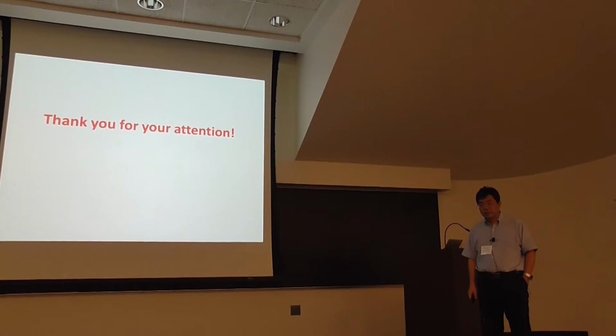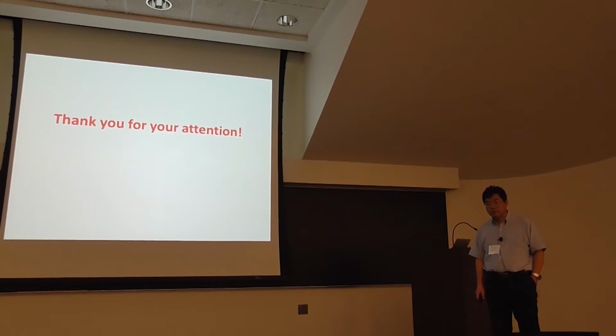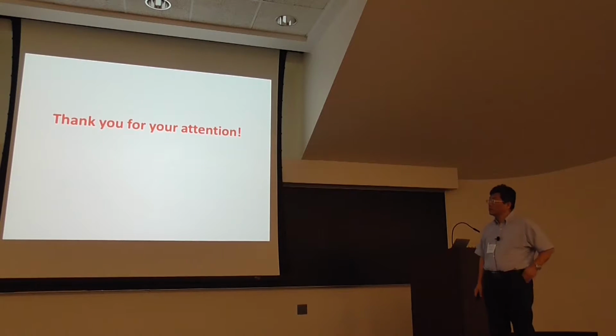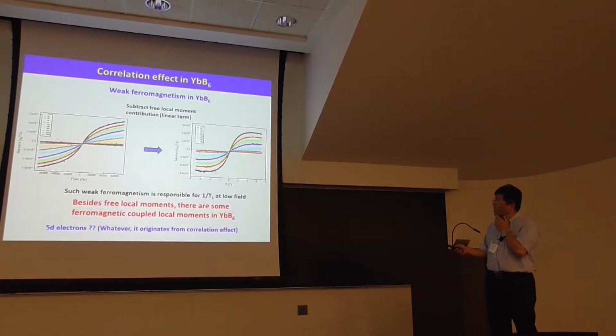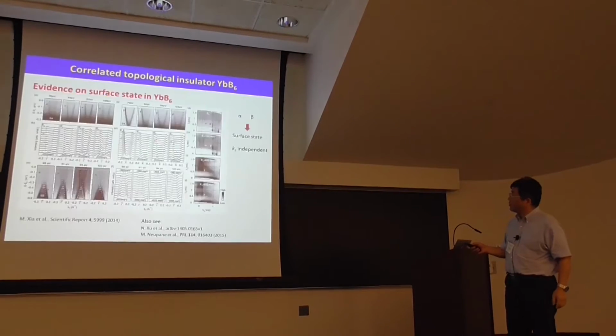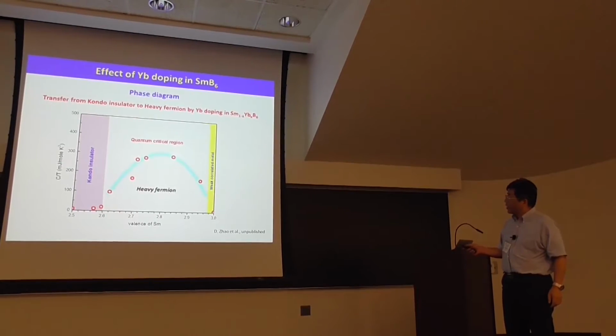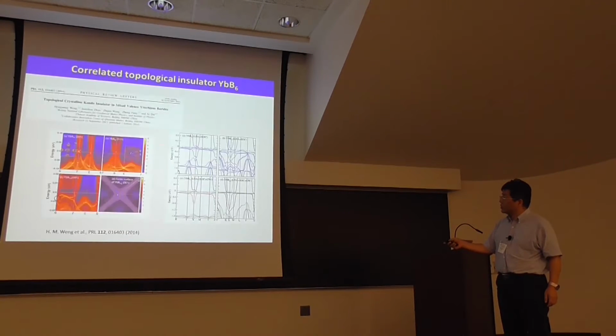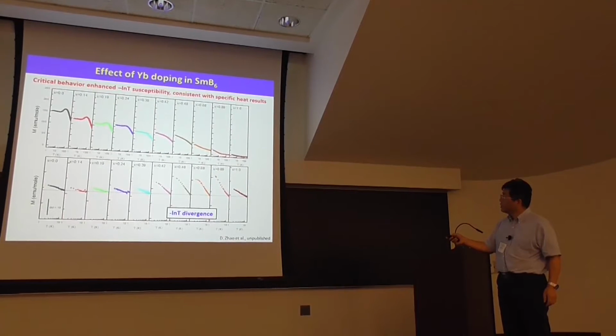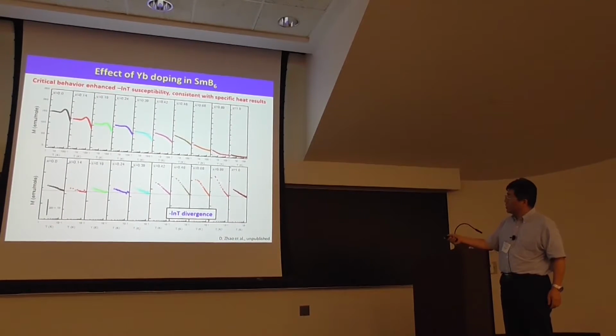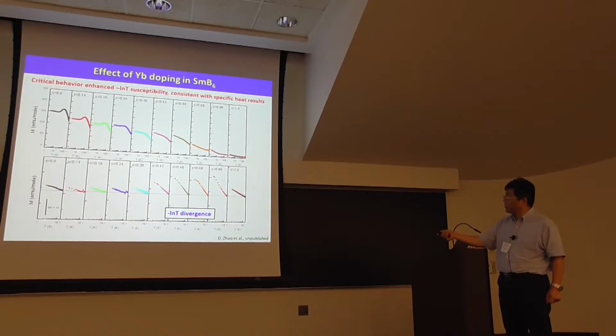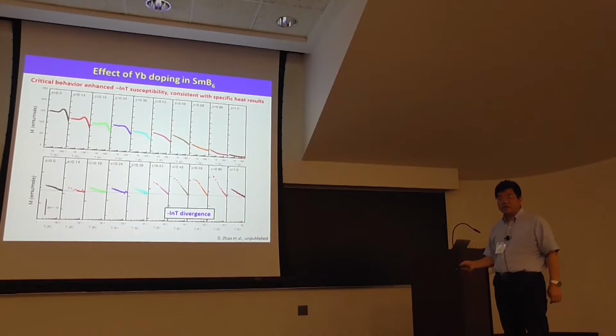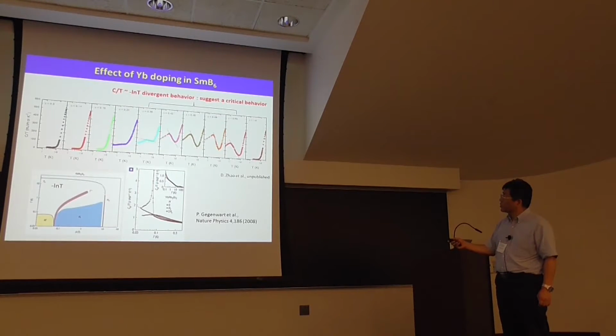What happens to the linear term of the specific heat? Does the linear term get smaller, larger, or not change? So the electronic term, the gamma term. Here is the gamma for the Ytterbium. In this region it should be larger. You can see this divergence. The magnetoresistance here is diverging in this region. I just chose the hybridization region, and the specific heat also shows this.